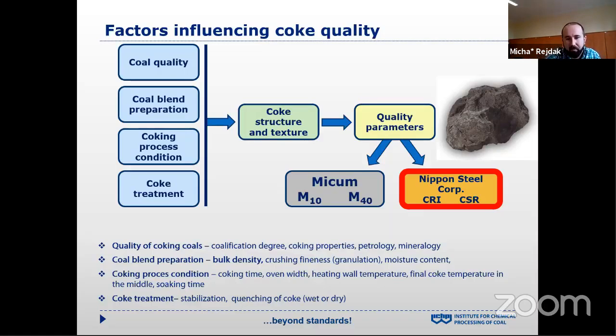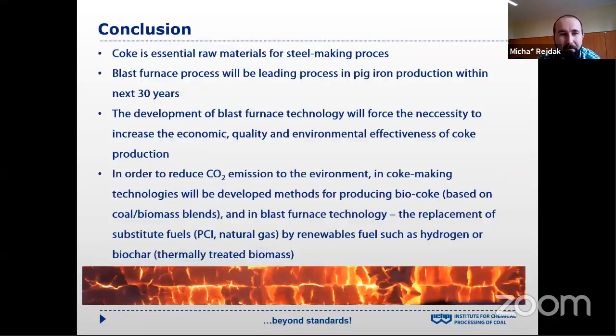But in the case of dry quenching, we can also extract the waste heat, which is lost in the case of wet quenching of coke. And of course, the gases are more delicate for coke structure, so they can influence a bit positively on coke quality parameters. And we are going to the conclusion.